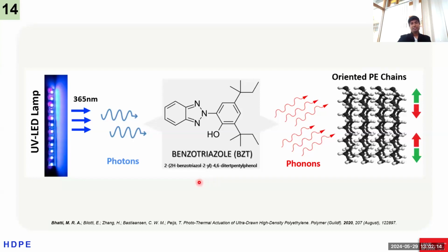I wanted to mention that the benzotriazole absorbs maximum light at a wavelength of 365 nanometers of UV light. So we use a light with that wavelength. The electromagnetic waves are absorbed by the benzotriazole, and in return, it generates phonons, which is vibrational heat energy. This vibrational heat energy is absorbed by the oriented polymer chains because the polyethylene is oriented. The chains are oriented in certain directions, and so anisotropic properties are there. So when these phonons are absorbed by the polyethylene chains, these chains tend to contract, rather than expand.